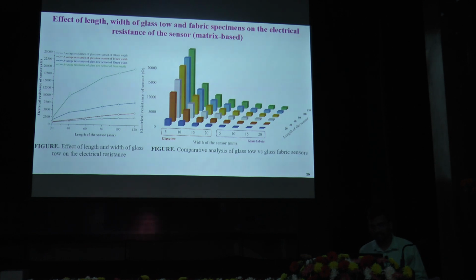This is the effect of length and width of the glass tow and fabric specimen based sensor on electrical resistance. From this graph you can see that when the length of the sensor increases, the electrical resistance increases up to some kilo ohm, and after that it becomes almost constant.